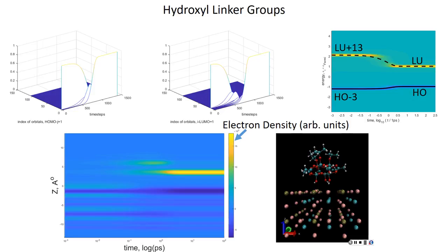So I guess ideally you would want this perovskite to stay more or less neutral so that it can keep exciting. But it happens really very quickly. At 100 femtoseconds, sub-picosecond range, you have already your charge transfer. So it probably has a really low chance to recombine back, because recombination will take much longer, right? You're not expecting that electron-hole recombination will happen in the femtosecond range. If you really have the right contacts at this energy range of your charge transfer state, then you really have no other channel to compete with such fast transfer.